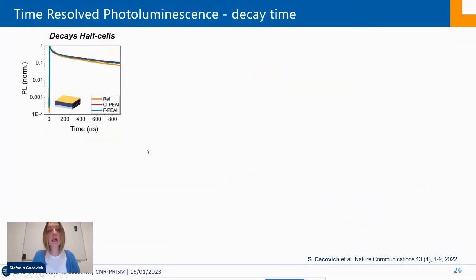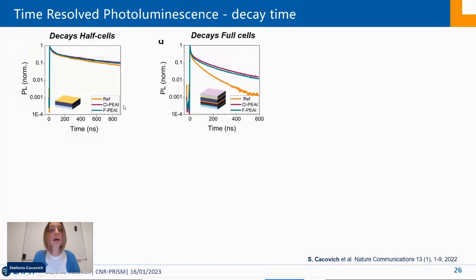Then we did the same analysis, but for time resolved experiment on half cell and on full cells. And again, what we observe is that the real improvement is after we added the transport layer. This means that it doesn't mean that there is only a surface passivation, but rather an interfacial passivation.